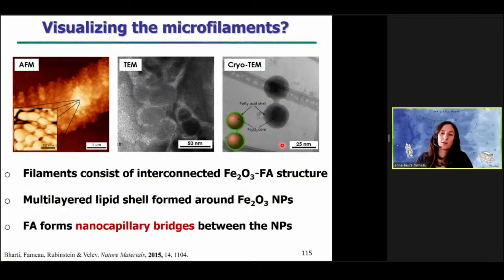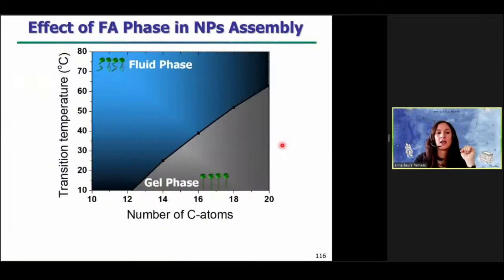So to better understand the effect of this fluid layer surrounding the particles, we decided to study the effect of the fatty acid phase, when the alkyl chains are in gel phase or in fluid phase, on the nanoparticle assembly. For this, we use differential scanning calorimetry experiments. We determine the transition temperature between the gel phase and the fluid phase as a function of the carbon number of the fatty acid soaps that we use to produce this kind of filaments.